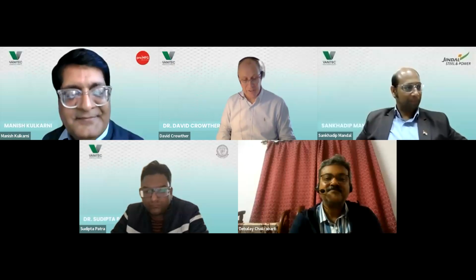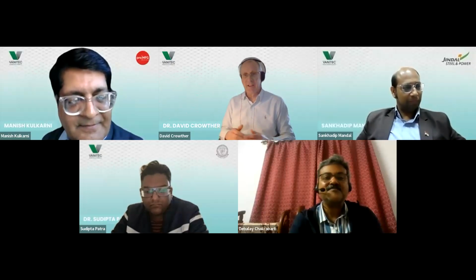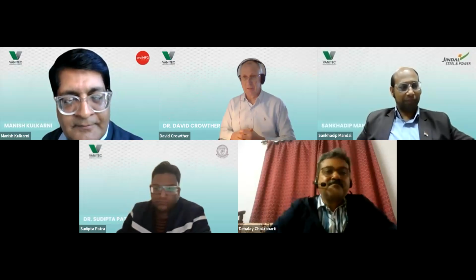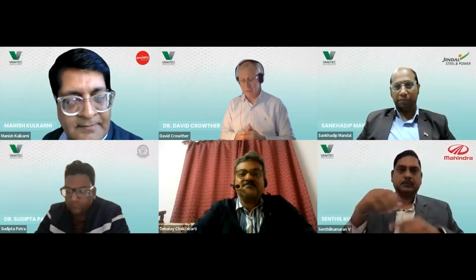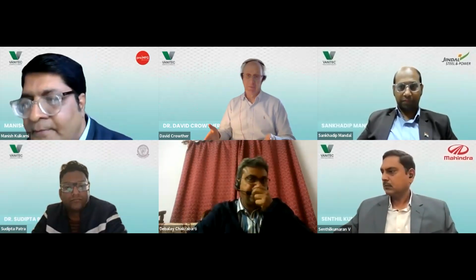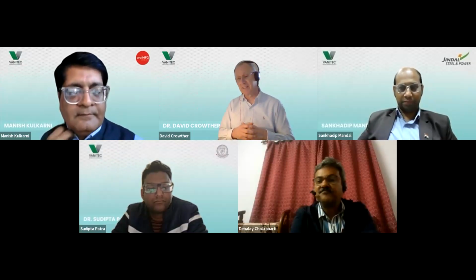Thank you, Manish. I'd just like to concentrate on a couple of aspects. First of all, I'd like to highlight the versatility of vanadium-containing steels. We've heard from many of the panelists that they've got experience of using vanadium in automotive steels or forgings, a wide range of steels. And I've mentioned that vanadium can be used in high carbon rail steels, for example, in high carbon rod and wire, but also in low carbon steel. So it's a very versatile element. And this relates back to the fundamental solubility of vanadium carbides and vanadium nitrides. They're very soluble compared with niobium, titanium.